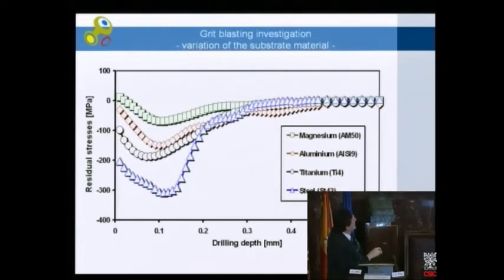You can read the types in detail, and you can see that there is a distinct influence in the compressive stresses. 0 is the outer geometric surface, and we have developed a method to determine the stress distribution not laterally, but in the depth profile. And what we can learn in a second is that the elastic modulus, the Young's modulus of the substrate material, has an important influence on this type of stresses as they occur near the surface or in the interface between the substrate and the coating.